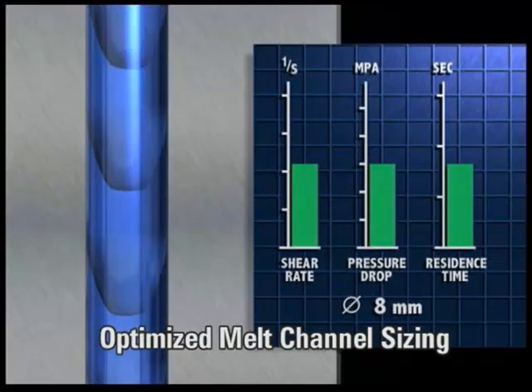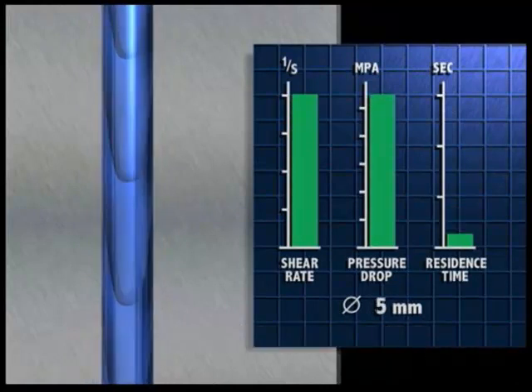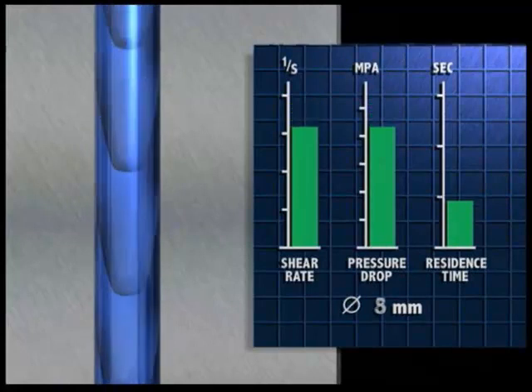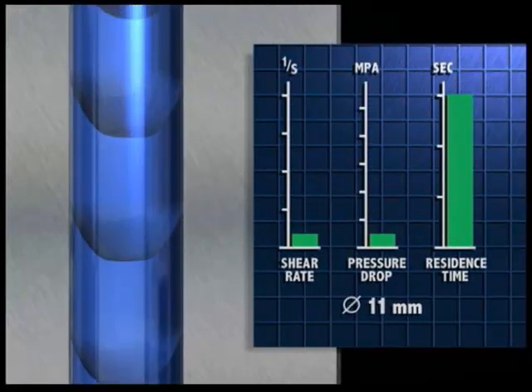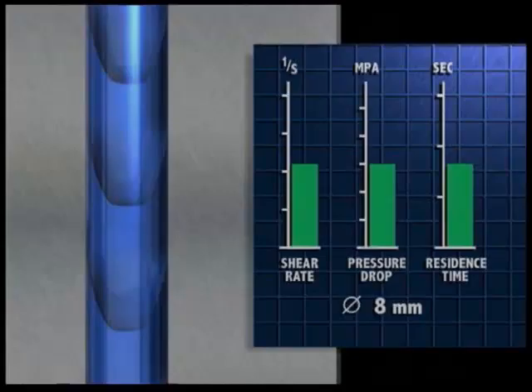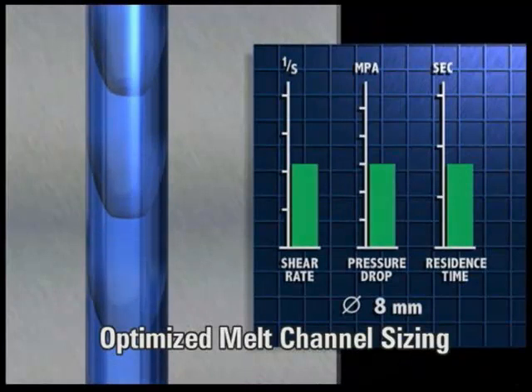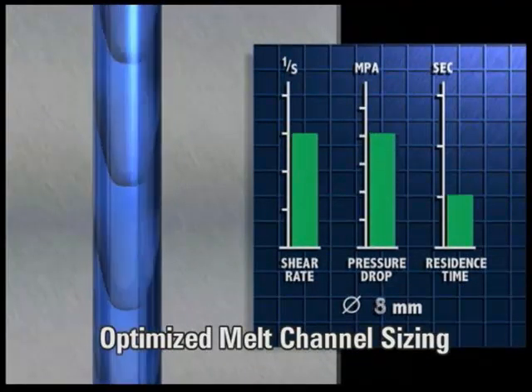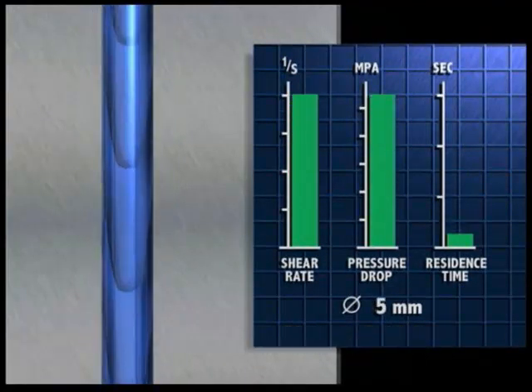So what we're seeing here is a melt channel of 8 millimeters, and now we're making it smaller. As you can see, the shear rate and the pressure drop will go up. Residence time will go down. If we do the reverse, if we're making the channel larger, I will rerun it once more. So shear rate, as we go smaller, goes up, pressure drop goes up, residence time is down. This is all good things for color change.